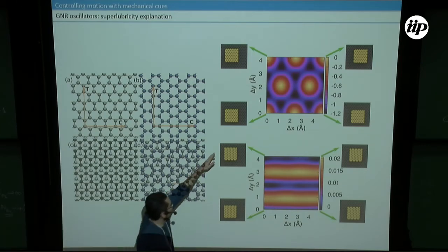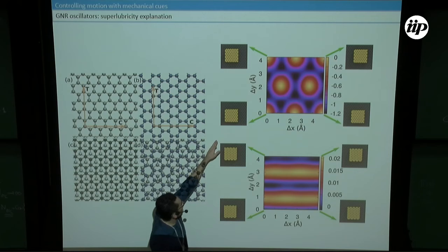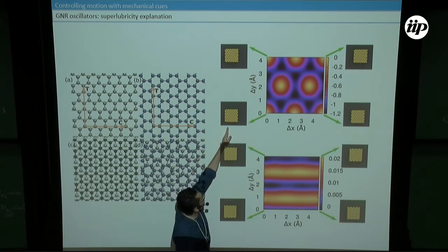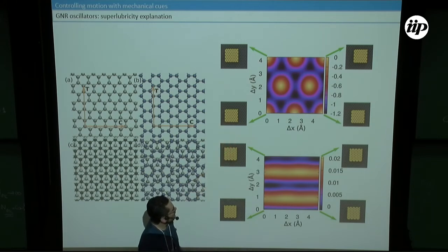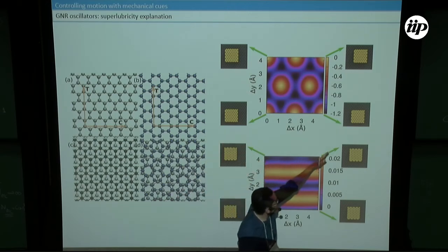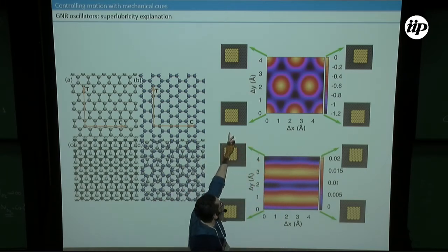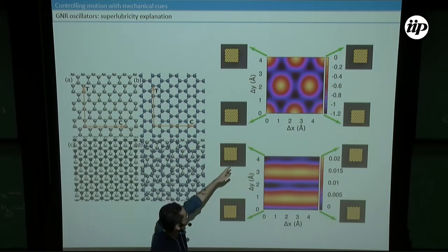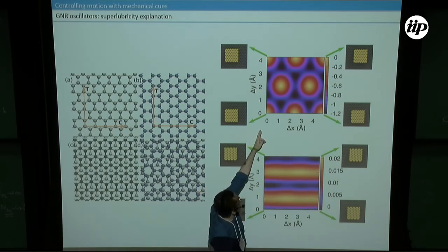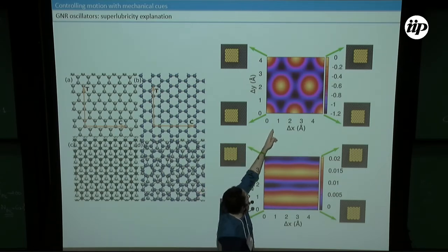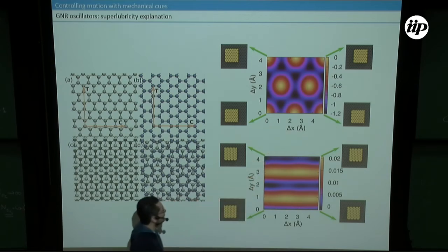And we actually did this kind of surface map. We put some graphene on top of the other, and we move it around the surface. We move it a bit up and move again. I think this map here has like 20,000 single point energies. So we move here and move all the way to the left, to the right, and then we move it a bit up and move again, all the way to the top configuration where it's at the maximum y displacement, and then we move again to the right. And you can see clearly here some maximums, some minimums. The maximums correspond to AA stacking, and the minimums, in deep blue, are the AB stacking.